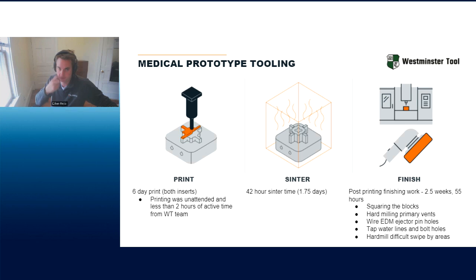The process for Westminster Tool was to print these prototype tools in about 6 days. They said that this was fully unattended, less than 2 hours of active time from their team, because it's that simple to set up and get this thing running. Sintering was about a 42-hour process, so about a day and a half. Then the final finishing work, which was 2.5 weeks, about 55 active hours, which was squaring the blocks, hard milling some of the primary vents, wire EDM of the ejector holes, tapping water lines, and hard milling just a couple of the difficult swipe by shutoff areas.